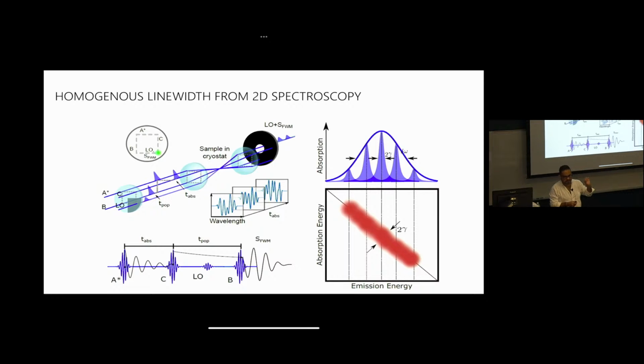But importantly, this is a bit where you really need to understand what the value of the experiment is. If I measure an absorption spectrum, I see a certain line width. And I can't tell you uniquely what is the contribution of that line width from the fact that there's heterogeneity in the sample, there's disorder, there's one exciton here at a different energy than there because of polycrystallinity and whatever, and the homogeneous line width, which contains the fundamental content of the optical transition, this dephasing process that I've talked about, right? I can't tell you that from a linear experiment.